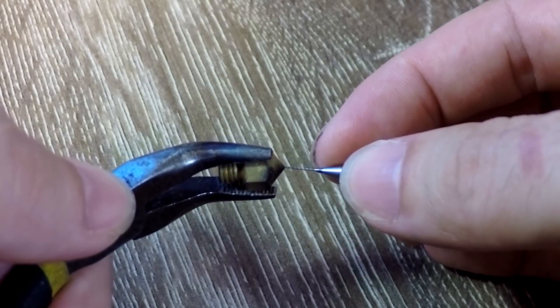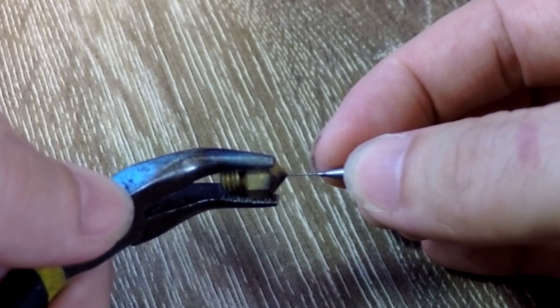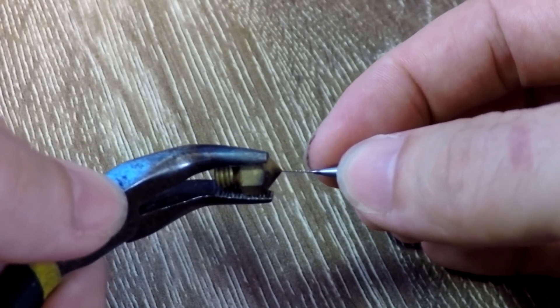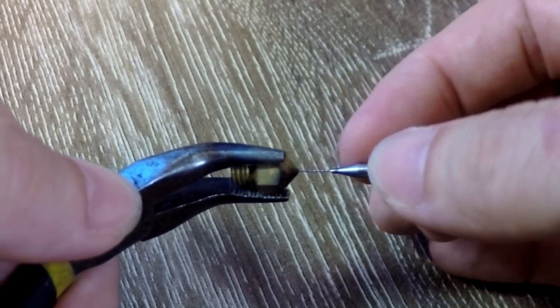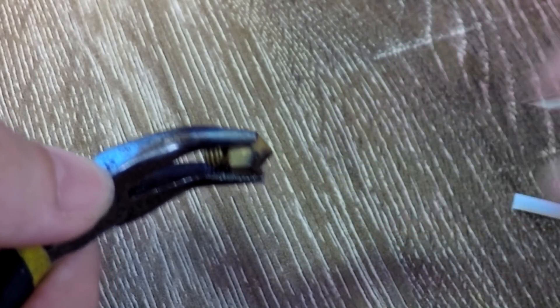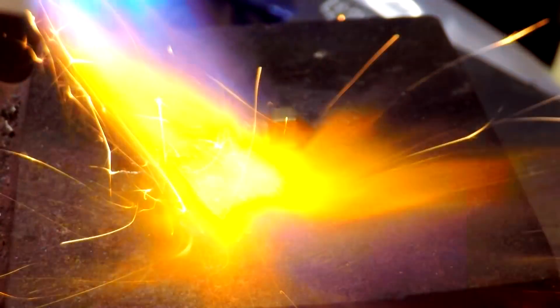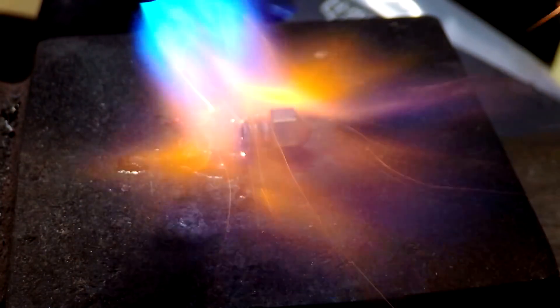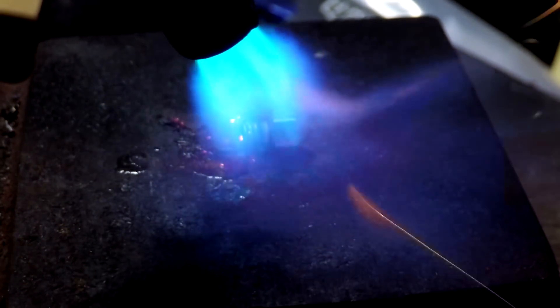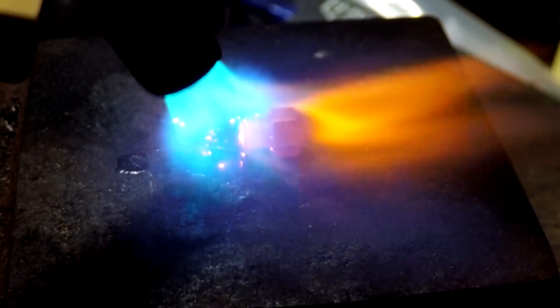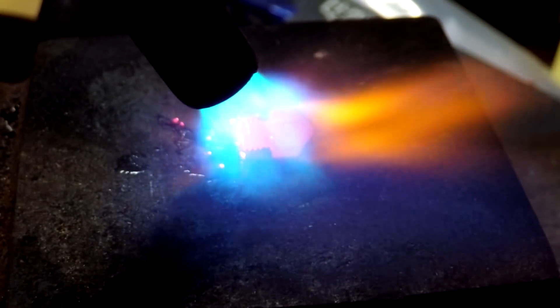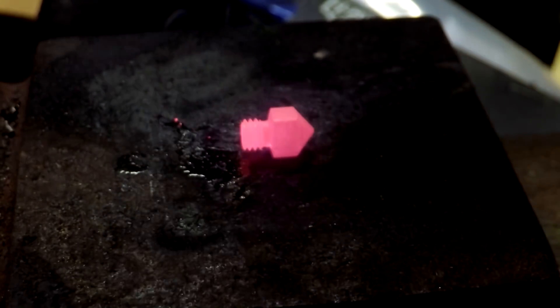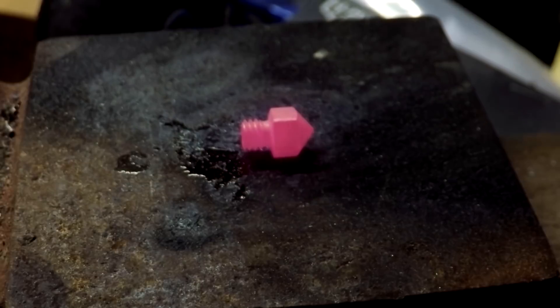The tiny drill bit that came with the tool set should only be used if the plastic inside the nozzle is hot enough to be melted. Otherwise you'll snap it. There is one surefire way I use to clean my nozzles. Apply a blow torch or a really hot flame to them until they're glowing light red. This will vaporize any plastic inside and after it cools down naturally in the air it'll be ready to reinstall clean as a whistle.